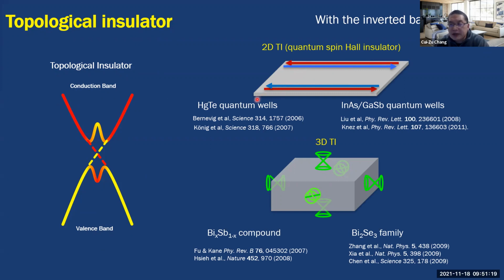The 2D topological insulator was first discovered in mercury telluride quantum wells. The 2D topological insulator is also called the quantum spin Hall insulator. Later it was found in indium arsenide and gallium antimonide quantum wells, and more recently in monolayer 1T' tungsten telluride. The 3D topological insulator was first discovered in the bismuth antimony compound, and later in the bismuth selenide family of materials, and later many more materials were discovered for the 3D topological insulator. In my experiment, we focus on the bismuth selenide family of materials for the realization of the quantum anomalous Hall effect.